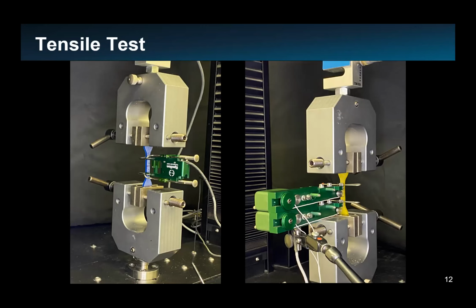So with the universal testing machine, we can perform compression tests and tensile tests. A tensile test is a type of mechanical test that measures the tensile strength and other mechanical properties of materials. During the test, the specimen is held between two grips, as you can see in the pictures, and the machine applies a force to the specimen in a vertical direction. This force is applied gradually, and the resulting deformation of the specimen is measured by a displacement sensor. In this case, for example, in the pictures, you can see two different extensometers. So I'm going to talk about the two different extensometers that we can use on tensile tests.